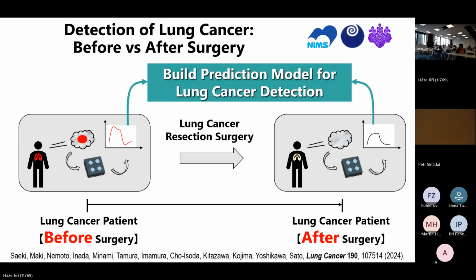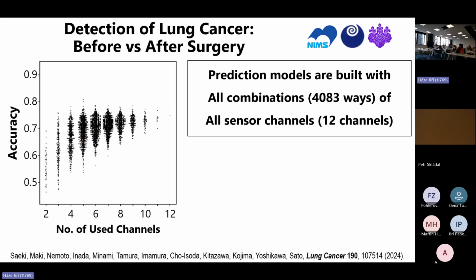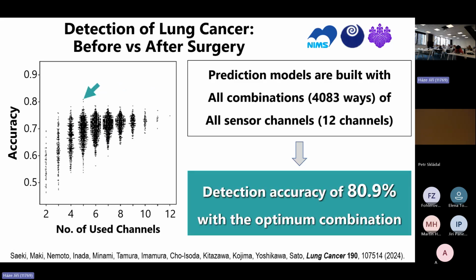Then we built a prediction model for lung cancer detection from these measured breath samples. We measured more than 60 samples, and for all combinations of sensors, we plotted the accuracy of each combination. We found that a certain combination of sensors can give a detection accuracy of more than 80%. This result indicates some possibility of using this type of sensor to detect lung cancer for screening.